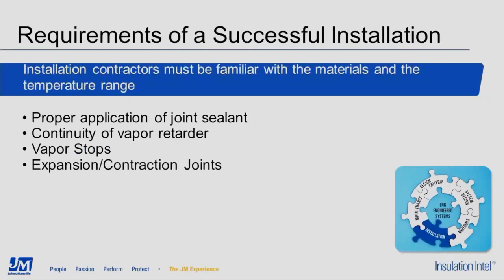One of the key issues is the proper application of the joint sealant. As Jim mentioned, it must be on both surfaces, thin layers, and definitely not on the inner layer, but a thin layer of the joint sealant on both joints that are going to be touching each other on the insulation materials. And the continuity of the vapor retarder: it must be installed without pinholes, without punctures, and it must be tight so it can function as the vapor retarder.